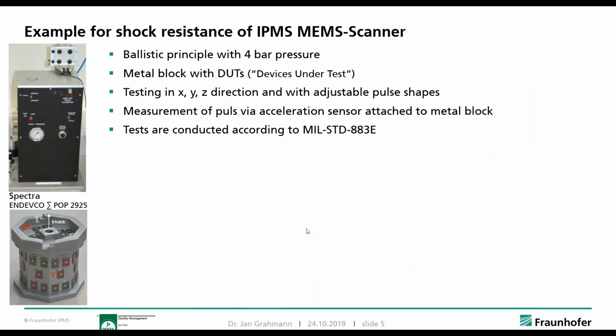And therefore we do make shock tests, and we use a setup shown here at the left side that allows us, with a ballistic principle and a pressure of 4 bar, to accelerate a metal block with the device under test. And on this metal block, which is shown down here, there are different scanner chips, or one scanner type, for example, stuck to that metal block, and we can then look into different directions in X, Y, and Z and test how the pulse shape, the shock really damages or not damages the scanning mirrors. So we do have an acceleration sensor that measures the pulse we apply to these scanners, and the whole test is conducted according to a MIL standard, that's a military and space US standard.